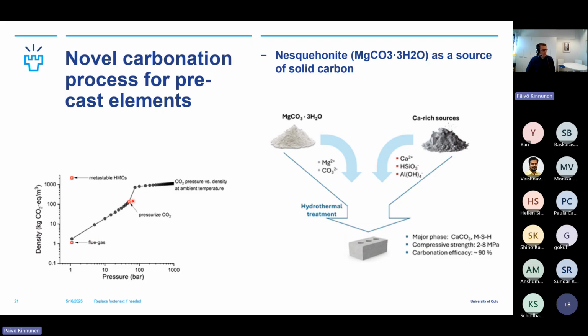So our question was, if you could start with the nesquehonite that we showed here, the density of the CO2 is actually orders of magnitude higher than the flue gas or even the pressurized CO2. And if you have magnesium oxide, you can react that directly with the flue gas. The reaction is downhill and happens at room temperature quite rapidly. So this is a way to avoid the first separation and pressurization, right? Because if you have to pressurize, this incurs costs to you.